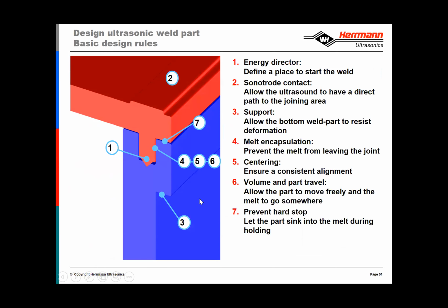Number 3, support. So the blue part, when loaded into the fixture, should remain motionless. Very often we have to apply relatively high forces in order to get the transfer of the mechanical vibration into the parts. And if the part in the fixture either is loose or moves or is not properly supported, and it's allowed to deflect, then we may get inconsistent welding results.